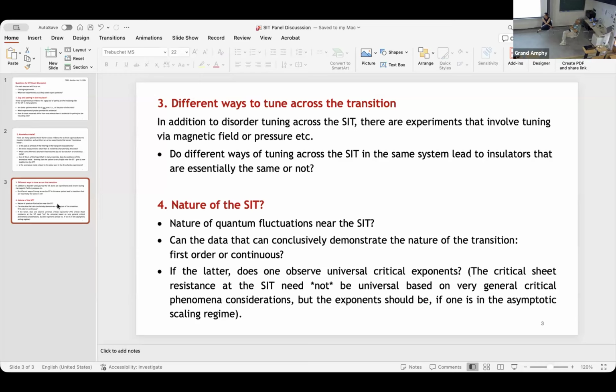I think I understand your reasoning, but in our experiments, and also when comparing to perturbative theory, if we put the sheet resistance as the independent variable, we always get smooth curves. What we have compared in our experiments are the KFL values that we derived from the 3D expression. KFL is an effective quantity. I don't know where the disorder comes from; it's some average. And we have seen that for KFL we get a more or less universal behavior, whether we are putting vacancies in the nitride or reducing the thickness. Beyond that, I don't know whether they are identical.